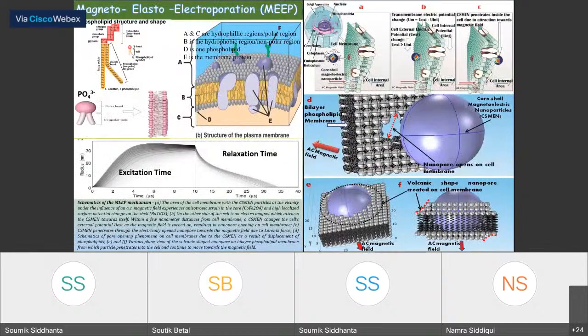Now, the idea here was that we have this phospholipid bilayer, which is a polar layer, where we have the phosphate head, which is PO4 3 negative, and the fatty acid chain. This PO4 3 negative makes the cell membrane a polar membrane. If we bring an electrical charge near, the phosphate head will try to deflect, especially if we bring a negative charge, the phosphate head will experience electrostatic repulsion and try to dislocate from its position. But the fatty acid chain will try to bring them back to their earlier positions, because of the hydrophobic effect.